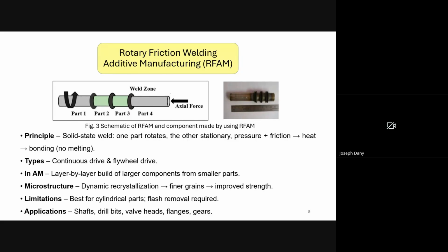But a couple of things to keep in mind are that this method mostly works for cylindrical shapes and creates different zones in the weld area that can lead to varying properties within the component. Also, the welded layer edges sometimes create excess material called a flash, which requires finishing afterwards. In industry, you will find RFW used for joining similar and different shafts, attaching drill bit shanks, connecting valves, welding pipe flanges and gears together inside the gearbox. Overall, rotary friction welding is a solid, reliable technique that is growing in use for building strong, high-quality components layer by layer.